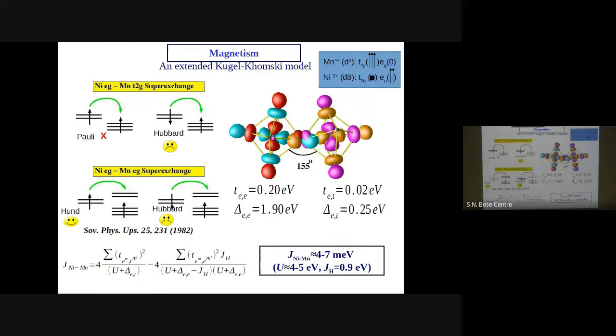Then manganese eg, nickel eg superexchange. There is another part. In this case, if they are both parallel, it actually still happens, because I think of this eg, which is empty, and that actually makes Hund very happy because in this way I'm maximizing the spin at a particular site. Hubbard is exactly the same thing. It can allow it, but it will remain unhappy because I'm putting electrons at the same site. So then what is the net magnetic exchange? It is basically the competition between these and that. Because this one allows a ferromagnetic channel, this one doesn't allow a ferromagnetic channel. So in this material, you have a ferromagnetic channel, you also have an antiferromagnetic channel. You have a competition between the two.